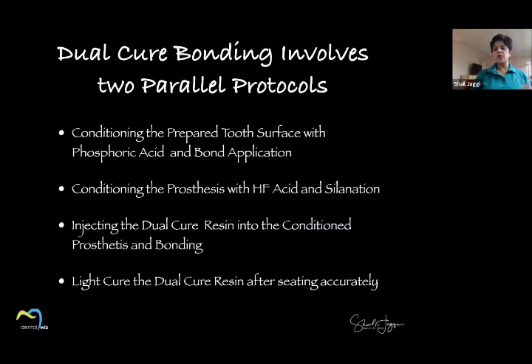So when you're doing a dual cure bonding, this involves two parallel protocols. Your tooth needs to be worked on and your restoration needs to be worked on, and they both need to be done parallelly. So how are you going to do that? You condition the prepared tooth surface with phosphoric acid and a bond application, condition the prosthesis with hydrofluoric acid and silanation, and inject the dual cure resin into the conditioned prosthesis and bond. Light cure the dual cure resin after seating it accurately.